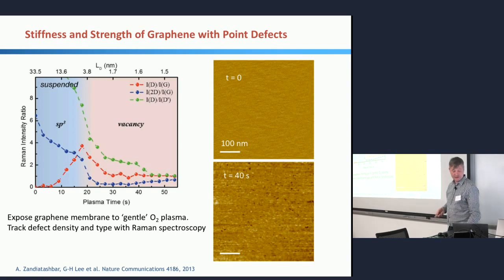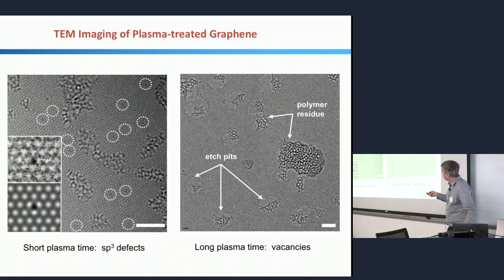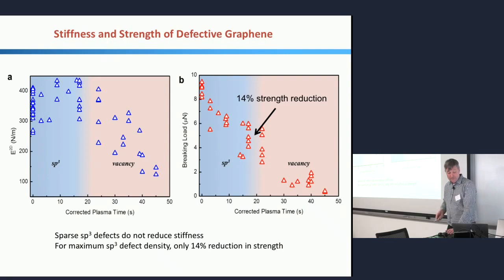So with that there's a crossover to the vacancy regime, and we're actually able to see that. Mauricio Terrones did some nice TEM for us, and we could actually see that in the sp3 regime we have oxygen add atoms, and then with longer etching, we actually start to make holes. So what we see with lots of experiments is the following. We see that the Young's modulus stays, again, there's a lot of scatter in the data, but it stays relatively constant as we add these oxygen add atoms.